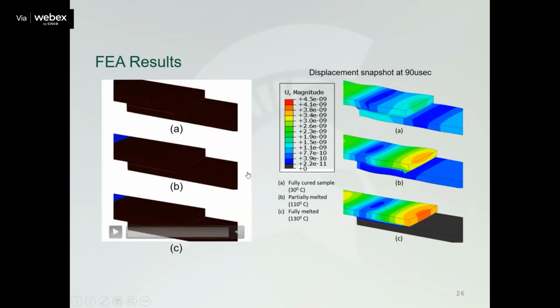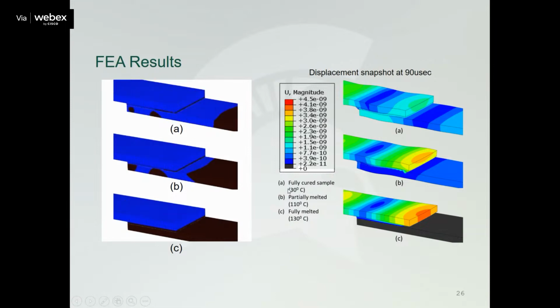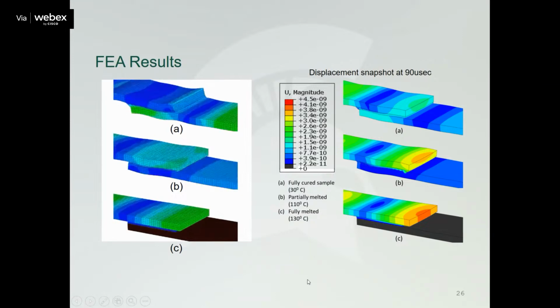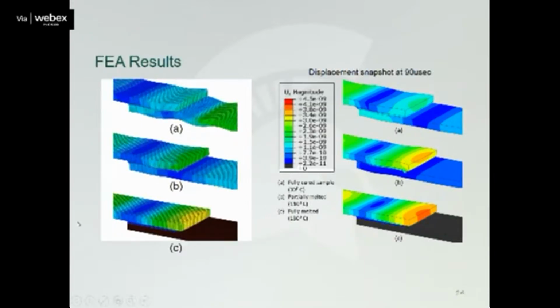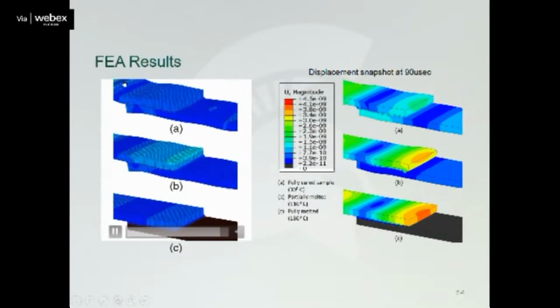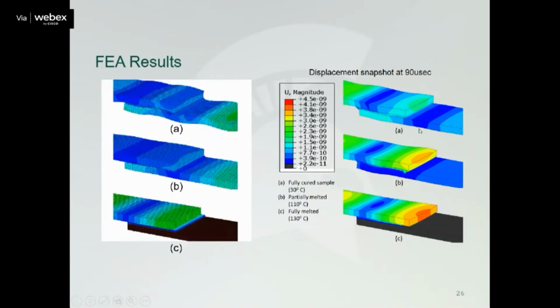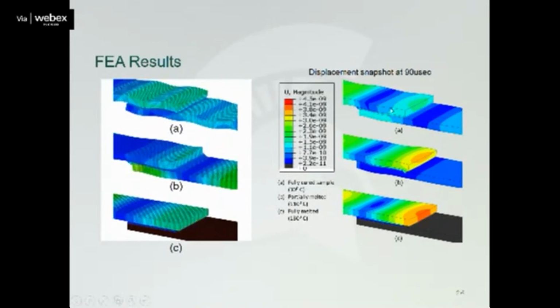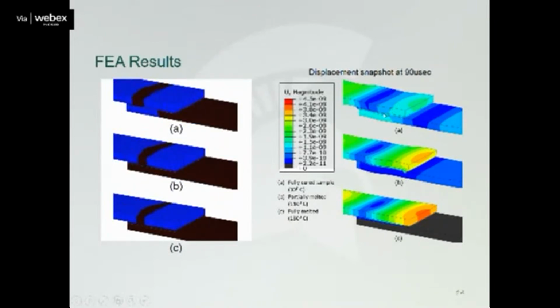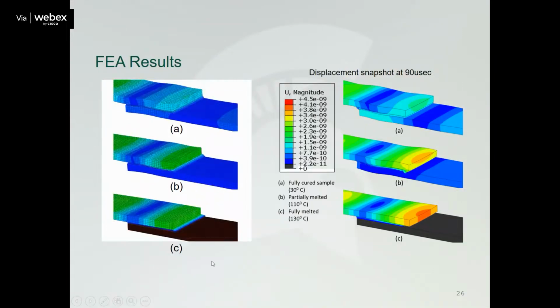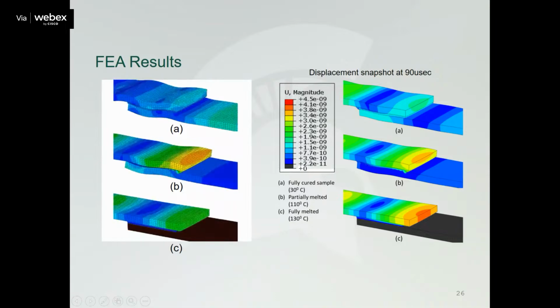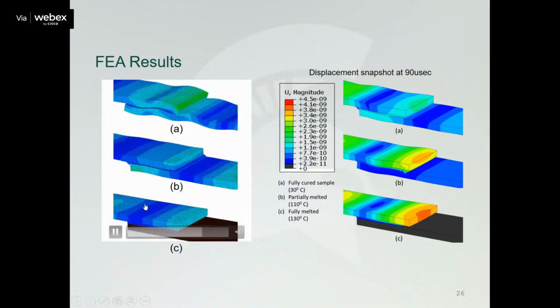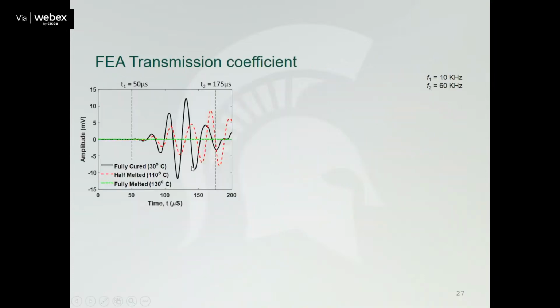And this shows you the FEA results, where you can clearly see for different temperature, you have a fully cured sample as source energy will be transmitted from one. Easy to see for fully cured, you have bottom, and you also have a displacement snapshot at one time instance, time 90 microsecond, versus partially melted. So the FEA clearly shows that at different temperature, how the adhesive will behave. So from that, we can calculate the transmission coefficient. These are the simulation study.